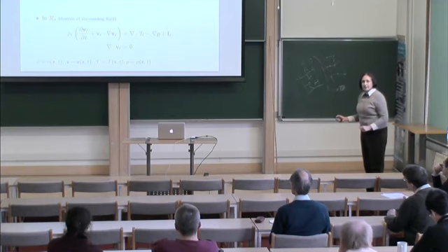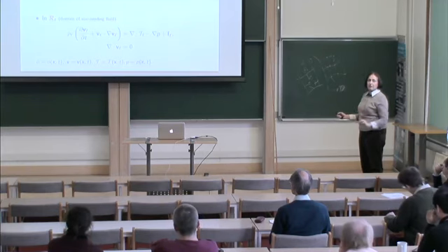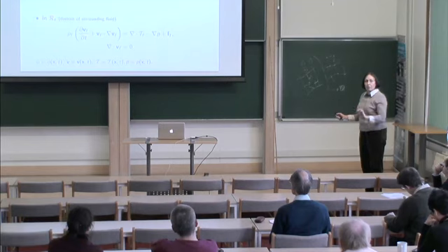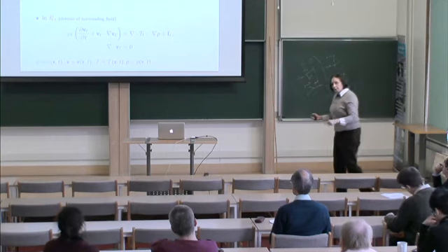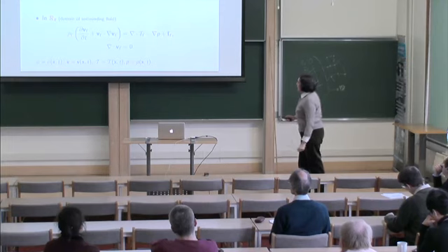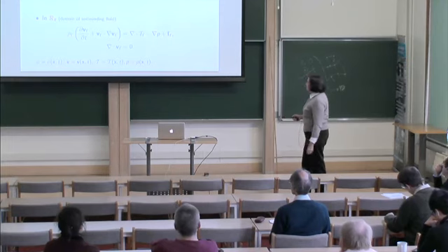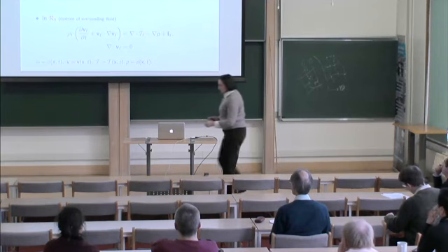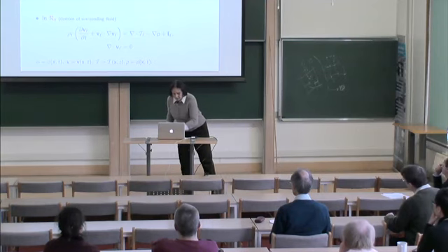And this, we're saying that the mixture is saturated, that there is either fluid or solid, there is nothing else. And in a mixture, you think of both components occupying the same point in space at the same time, but of course they occupy it with different volume fractions. Okay, and here we're going to have these velocities, stress tensors, pressures, and volume fractions. And later on we're going to see the ions.